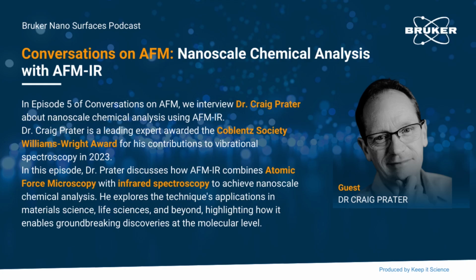So, for example, if you were to use a microscope using visible wavelengths, you'd be able to get a pretty sharp image with spatial resolution down to a few hundred nanometers. But if you replace that visible light with infrared light and try to do the same measurement, the image becomes blurry because the infrared wavelengths are an order of magnitude longer than the visible wavelengths. So instead of having spatial resolution of a few hundred nanometers, you have spatial resolution of several to many to a few tens of microns. And so, that's very, very coarse compared to the spatial resolution of an AFM.